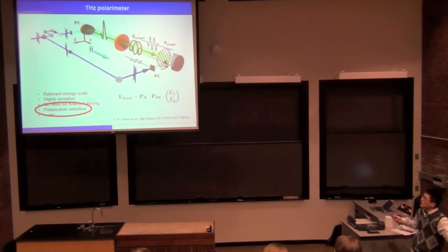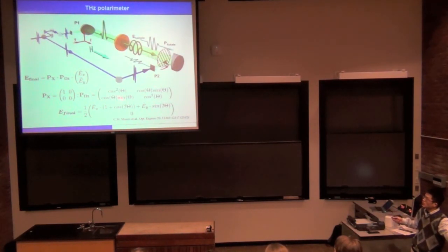If you write down the Jones matrices for this type of light path, I should say before the detector we have another polarizer. So you can see we have this vector describing the electric field of the Terahertz pulse here, and then this is the matrix describing this rotating polarizer, and then we have another polarizer. If you do the math, this rotating polarizer can be written by this, and looking at this, you realize there's a 2 omega component, twice the angle position component here, and then the final result is this. So we feed the signal into a lock-in, and we lock in at twice the frequency here. So the 2 channels measure EY and EX separately. This is how we do the Terahertz polarimeter experiment.